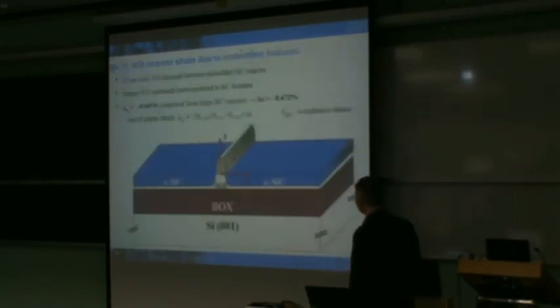The more important effect is looking at structures in which we have a finite volume rather than an infinite, what can be considered a very thick silicon substrate. We can interrogate both the silicon and insulator as well as stressor regions, again, if they're crystalline. And the advantage of looking at silicon on insulator technology, in which we have a very thin silicon layer bonded to the underlying substrate, is that we can actually map the diffraction condition, and therefore the strain that's generated, both independently within the silicon and insulator as well as the substrate.